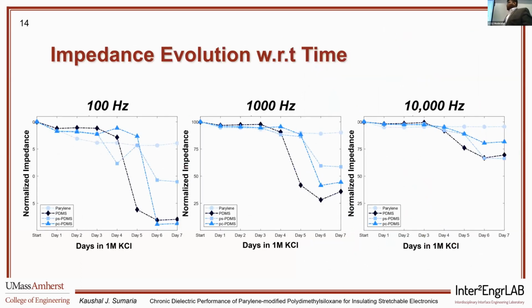We also plot the evolution of impedance over time for 3 different frequencies. And if you look at the trend, consistently the parylene layer performs better than the 3 other layers. The PDMS and the higher temperature pc-PDMS deteriorate much more compared to the other samples here.